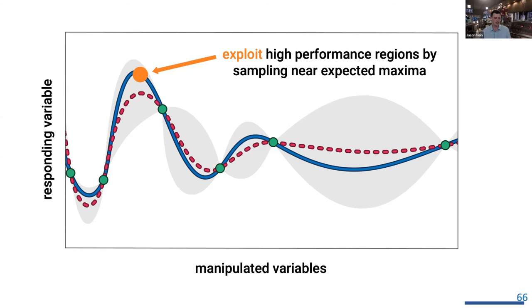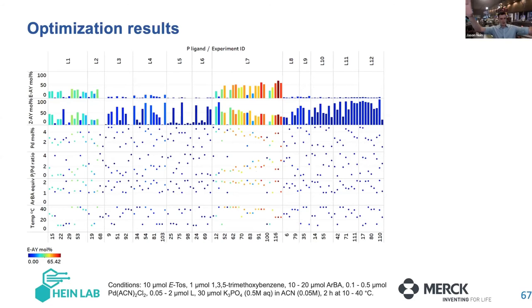So using this one, what I can happily say is that this is a tableau vision of what we've done here. And again, it's an ugly graph, but we have yet to figure out how to visualize 10-dimensional space easily. All we're trying to represent is we have multiple ligands that the system ran. We have sorted them in terms of which ligand and how they performed. And what you get from this is L7 seems to be performing very well. It actually has the highest yields of our E product, but more importantly, what we're showing down here are the conditions associated: the temperature, aryl boronic acid equivalents, palladium ratio that associate with each of those.